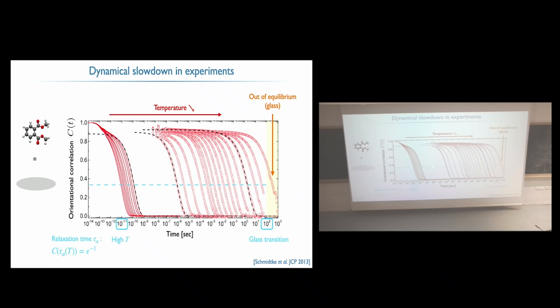And if you want to define a typical time scale, which is when it reaches, for example, this plateau, you see that it increases, and it increases in log scales. So this is really the more dramatic part. And at some point here, the glass transition, this is 100 seconds. So if you're doing an experiment and you wait 100 seconds, it's already quite long.